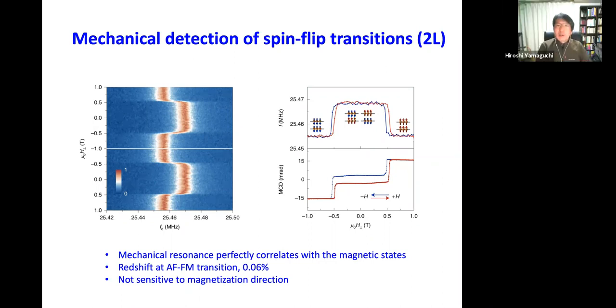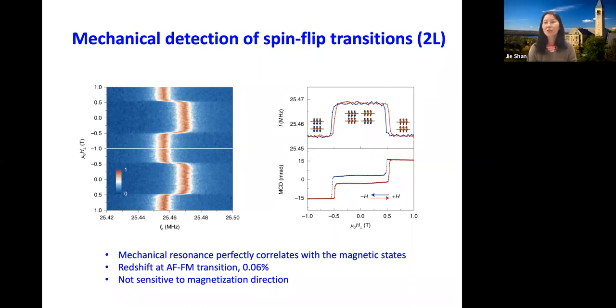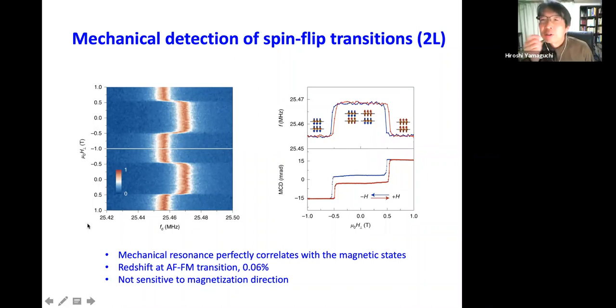Okay. Thank you. Okay, this is the last question, given by Andre. Thank you for a nice talk. Is the Q factor of these structures sensitive to antiferromagnetic and ferromagnetic transitions? Okay. Yeah, so the Q factor actually is not very sensitive to the transition, as you can see from the data. The width of a resonance basically doesn't change, and the frequency shifts by a tiny amount. I'm talking about a 0.1% change in the frequency.